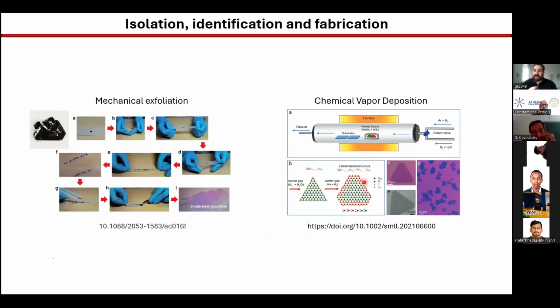You can end up having a substrate full of monolayers, larger than the ones that come out from mechanical exfoliation. But in this case, up until recently, the materials had a larger defect number than the ones that were exfoliated. And you don't want defects because defects can be the reason why you might disrupt the moiré periodicity. Of course, the CVD method actually had a lot of advancements recently, and I think it's getting better and better.